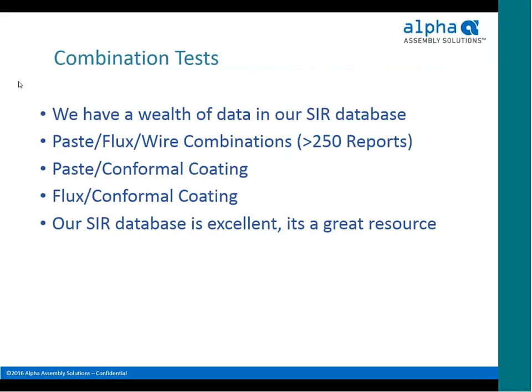Well, we can test them in combination to determine whether or not there's a synergy amongst those materials that could potentially take four different materials that pass SIR, but when used together, maybe don't give you the same excellent results you're expecting. We can also test the combinations of pastes or fluxes and conformal coatings that go over them, especially in the dewing or the cyclical temp and humidity tests. So those are great resources.